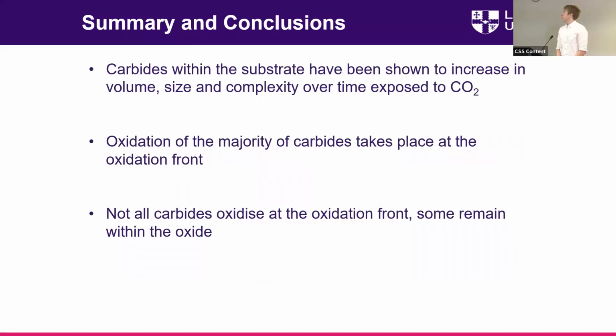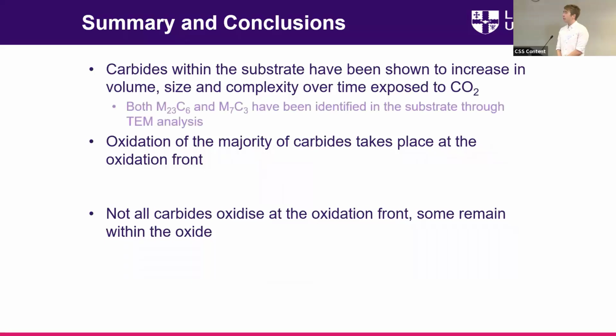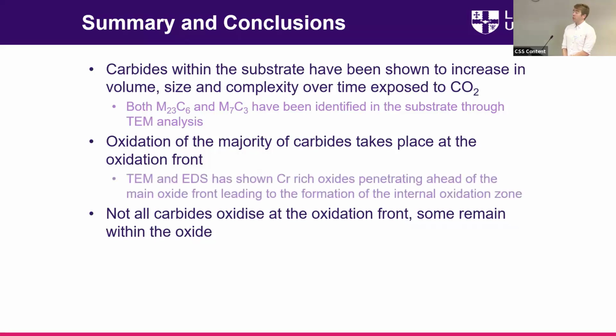So just onto some of the summary and conclusion. The carbides within the substrate have been shown to increase in volume, size and complexity over the time exposed to carbon dioxide, with both M23C6 and M7C3 being characterized in there. Oxidation of the carbides, the majority of the carbides, takes place at the internal oxidation zone with preferential oxidation of chromium.